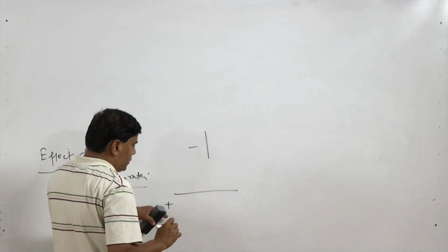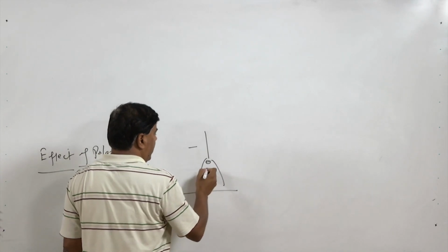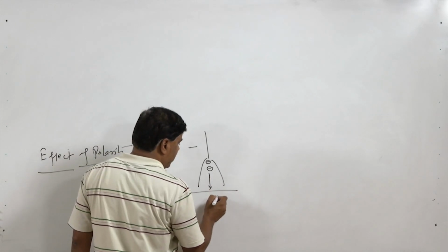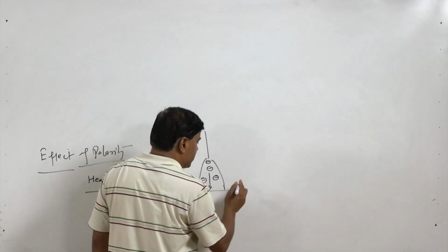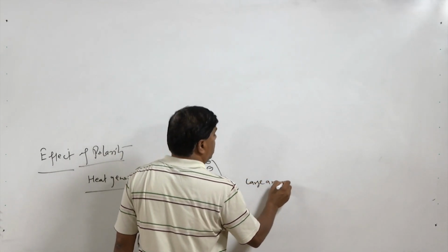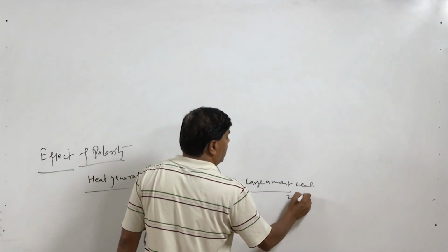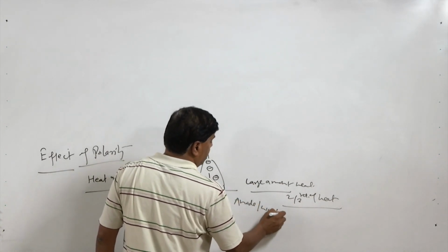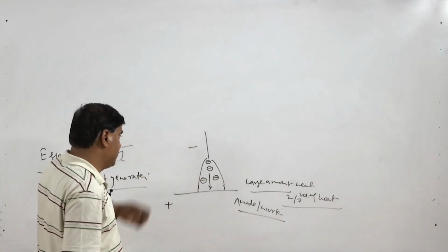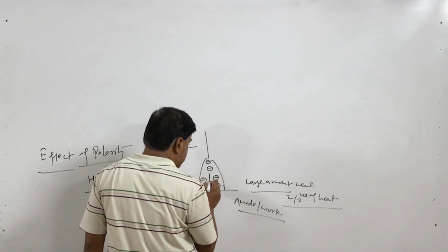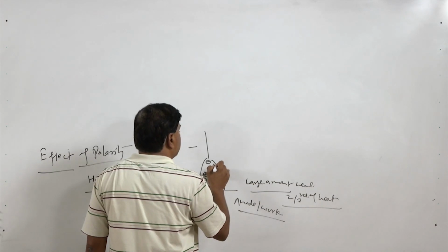This is very important. When straight polarity is used, the workpiece is connected to the positive and the electrode is negative. In this case, electrons are emitted by the electrode and keep on moving towards the workpiece, striking it, and the impact generates a lot of heat. Since a large number of electrons continuously impact the workpiece, a large amount of heat is generated, about 2/3 of the heat, on the anode side. So, the anode or workpiece will get much more heat as compared to the electrode, while at the electrode the ion current is very limited, about 1 to 2%. Here the heavy ions will move very slowly towards the cathode and impact the electrode at a very low velocity.